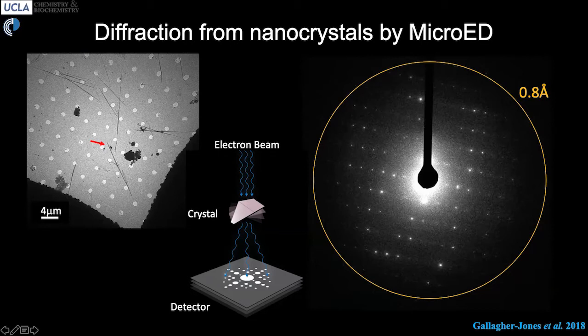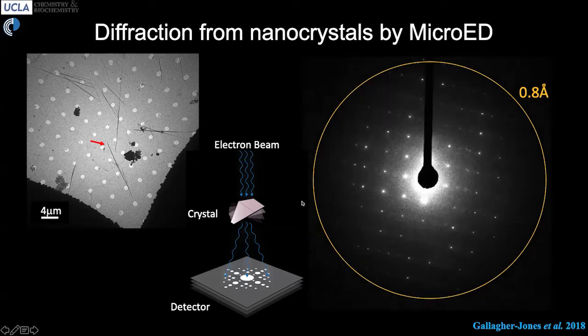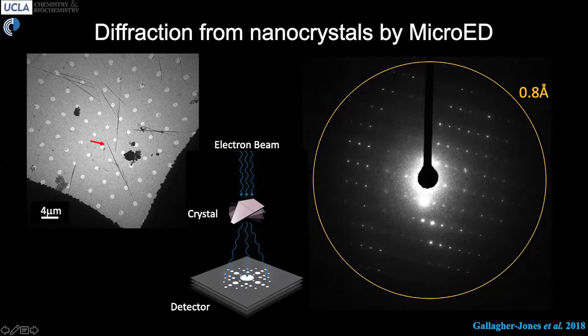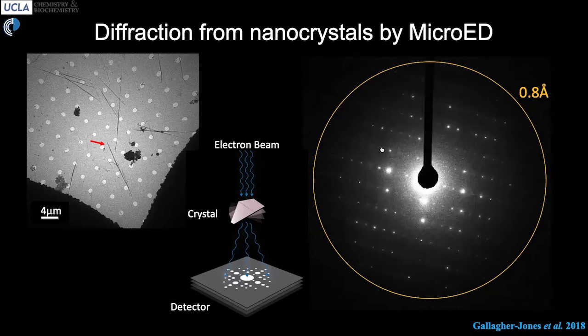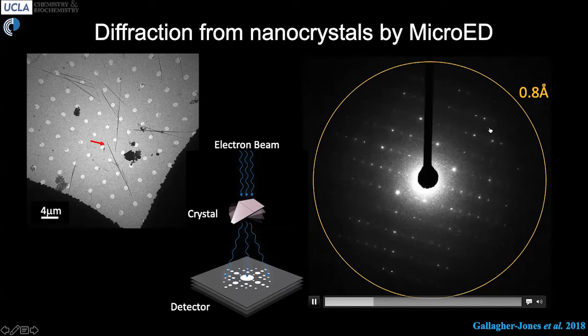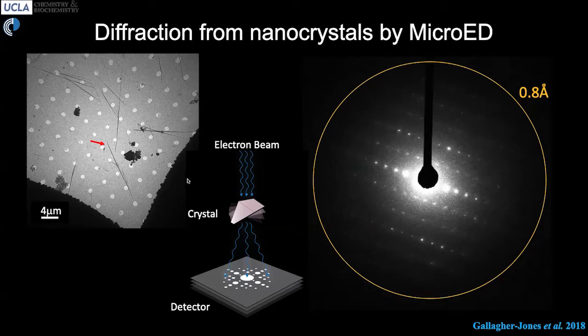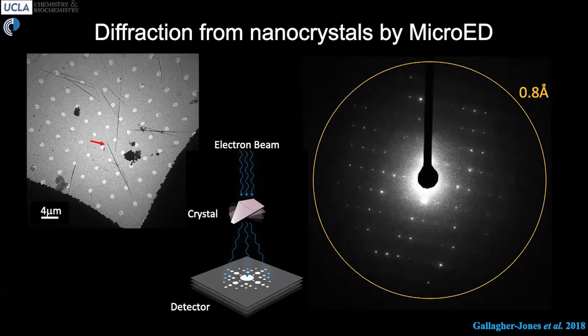Then we placed an aperture inside the microscope to select diffraction only from the tiny tip of this needle. From that, we collected a movie that looked like this as we were rotating the sample within the electron beam. And you can see, again, spots that represent constructive interference at particular locations in reciprocal space. We can see that the extent of these spots represents a resolution of better than 1 angstrom for this diffraction. So we were really excited by that. This led to solving the structure of this molecule from this data set.